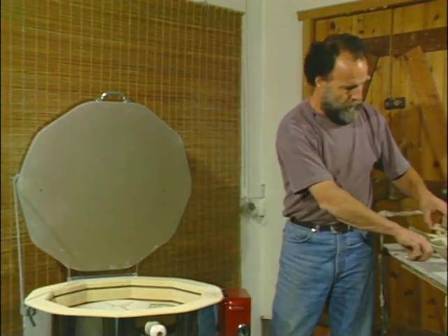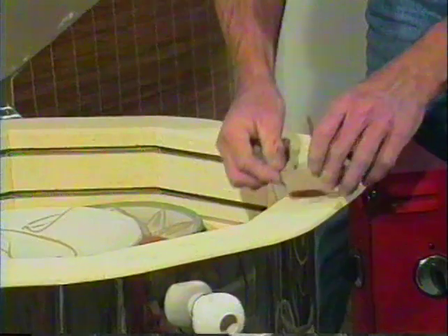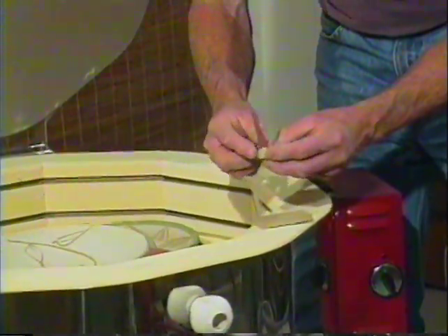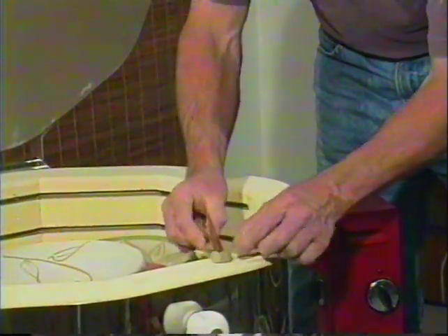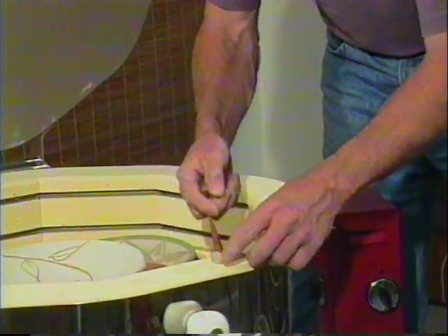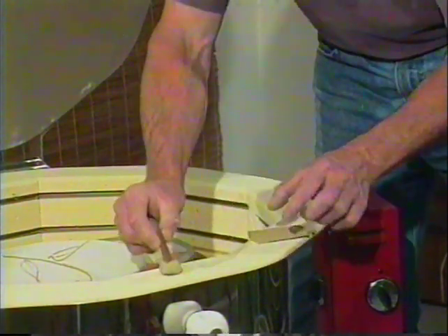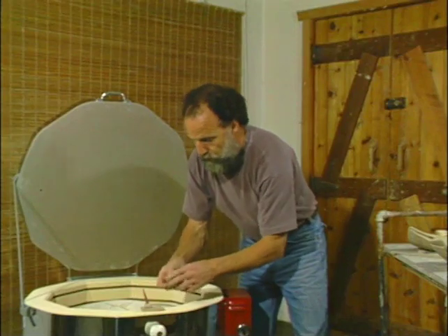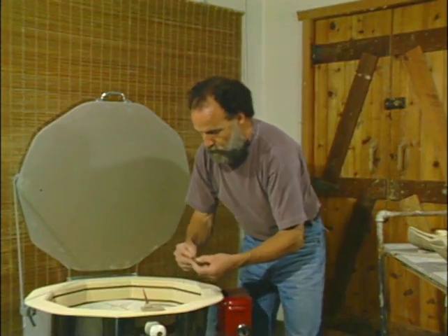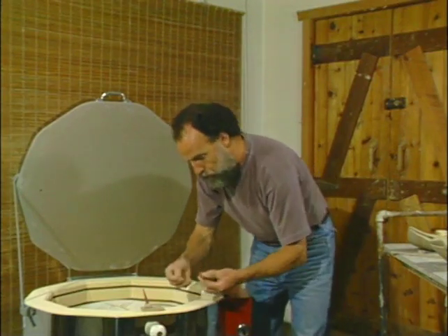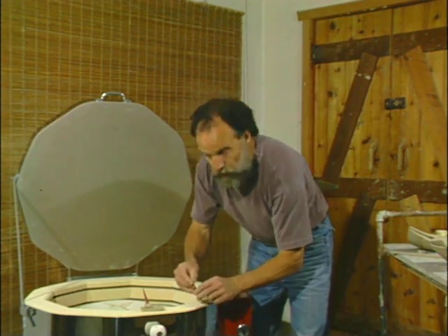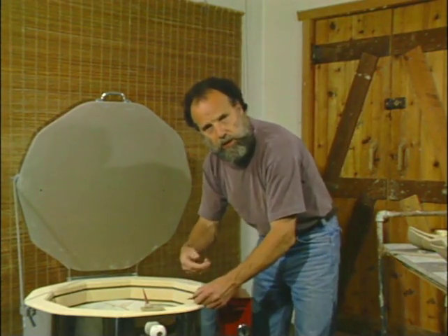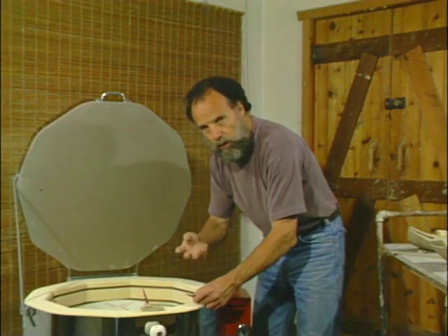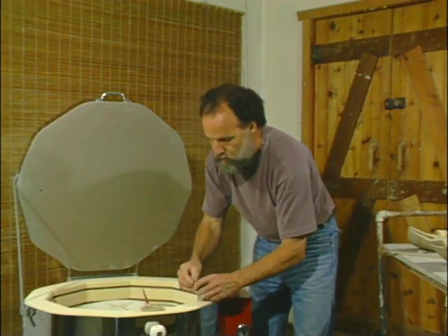Now, I've made this cone a couple of days ago so that the fresh clay around the bottom is as dry as the bisqueware, otherwise you're going to have a little explosion here because of wet clay. So what you do is, this is an 010 cone for this bisque firing. It's important to read the instructions in the cone book. That'll tell you quite explicitly how to place these cones.